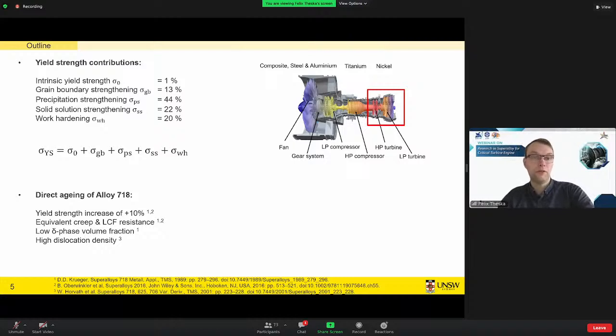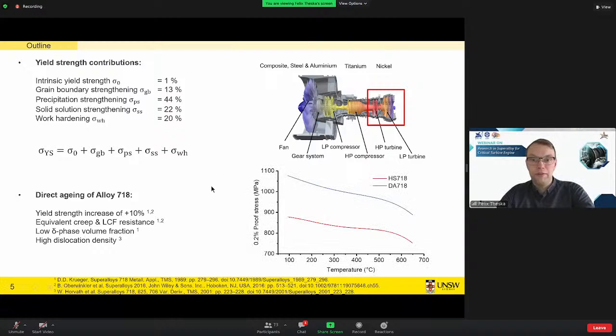What we also know already is that the delta phase volume fraction is lower and we have a higher dislocation density. When we look at the temperature range of conventionally high strength 718 compared to direct aging of 718, we find quite a major improvement.